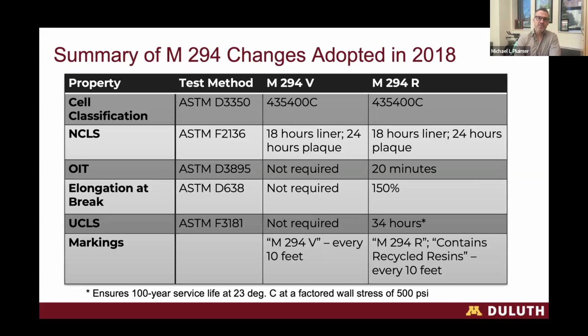Some of the changes that went into M294, we basically have two categories now of pipes in there. M294V represents pipes manufactured with virgin materials, and M294R represents pipes manufactured with recycled content. You can see that the material requirements are the same for both of those. Both meet cell class 435400C. Stress crack resistance, in accordance with the UCLS test method, is the same for both. We do require a 20-minute OIT requirement for the pipes manufactured with recycled content, and that's some added assurance that there's enough antioxidants in that material to protect it and stabilize it against oxidation. And then we have an elongation at break test that's required on the recycled materials, and as we mentioned earlier, a 34-hour UCLS test requirement, which ensures a 100-year service life at 23 degrees C.